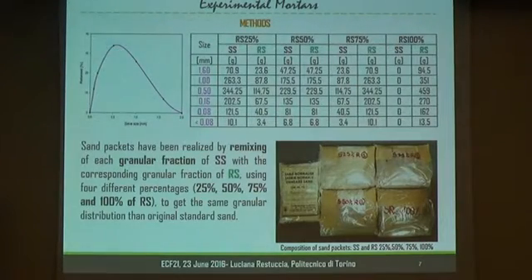For this reason, both the standard sand and recycled sand were sieved according to the retained size mesh of the standard sand. So we sieved the standard and the recycled sand into 6 granular fractions. We decided on 4 percentages of replacement from 25% up to 100%. And so the sand packets have been realized by remixing each granular fraction of standard sand and recycled sand, obviously to get the same granular distribution.